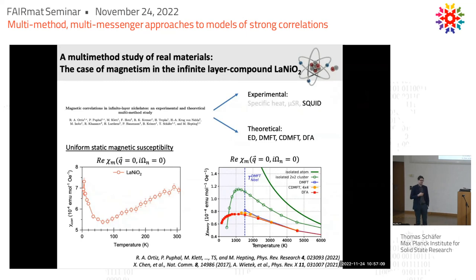Yeah, so in principle there exists a scheme which is recognized as being, in a certain sense, generic, but then also not really. It's the LDA plus DMFT scheme. What you do is you do your DFT calculation, then you project on the Wannier states, get the Wannier states, you do a cRPA, which gets you the interaction parameters, and from the Wannier states you get the tight binding, and then you can go to Hubbard and DMFT. So this is the usual thing.